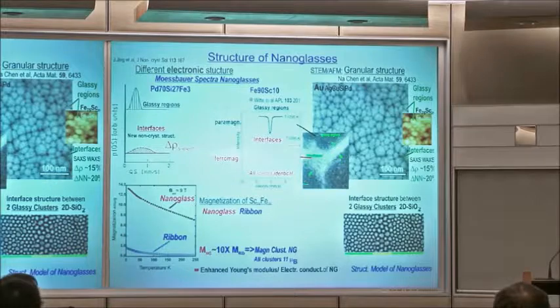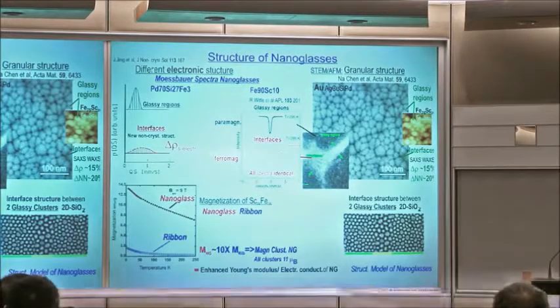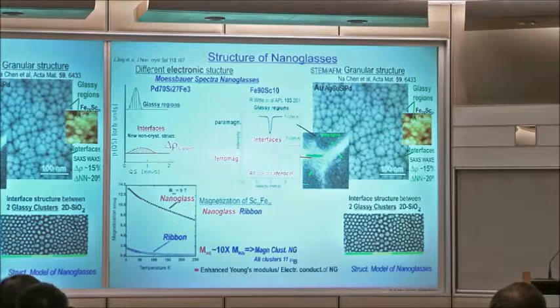What we do not know at the moment is what the atomic structure is. The reason is very simple. In order to do ab initio calculations, you have to know where the atoms sit, but we do not know where they sit exactly at the moment. We are doing some experiments, but if we knew that, then we could do the electronic structure. But to get the electronic structure, you have to know where the atoms sit, and in order to know where the atoms sit, you have to know the interaction between the atoms. So all we can say is densities, modulus, electric conductivity. We can always get a result which averages.